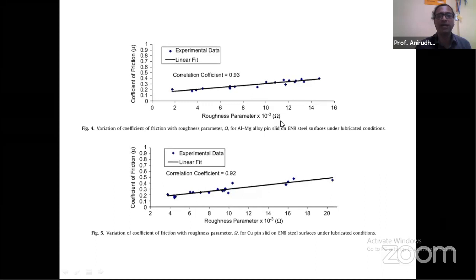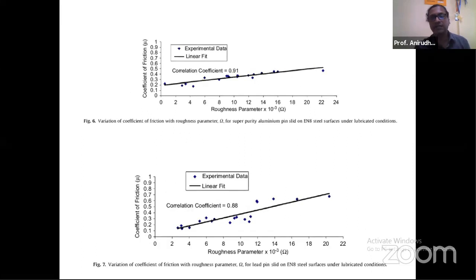A small value of this parameter, which is at this point, corresponds to a low value of friction due to ploughing, friction due to asperity interlocking, and roughness. Whereas a large value of this parameter is indicative of a high value of friction. So this is for this experiment for aluminum magnesium alloy. Shown below are the experiments under lubricated condition while using copper pins. In the next slide, you see the variation of coefficient of friction under lubricated condition when you are using a different material, aluminum. And similarly, you get it for another different material, lead, and things like that. There are differences also. We have explained all these things in that paper.